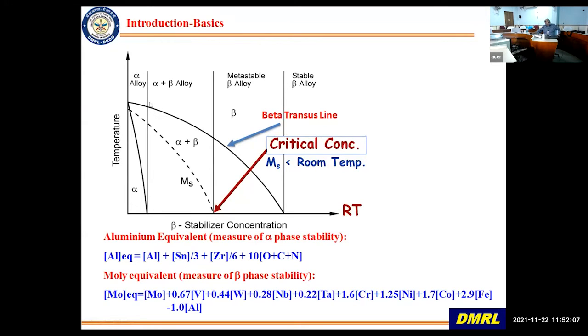Then you have, in between these two lines, what you call alpha plus beta alloys. And I will show you the examples also. Now, if you see here, this is room temperature. So wherever this martensite start line crosses room temperature, that is where you have this alpha plus beta alloy category, because that means if you quench an alpha plus beta alloy from above the beta transus, you are going to form martensite at room temperature.